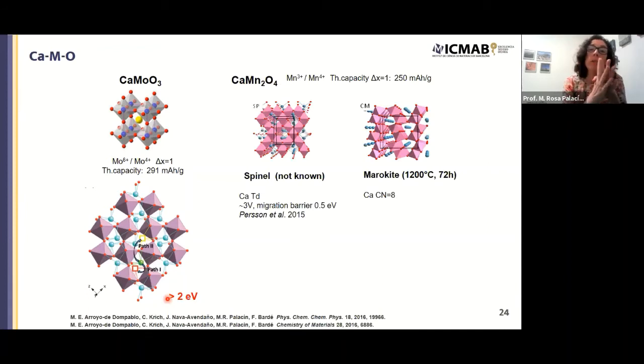Then we became interested in CaMn2O4. This compound had been studied by the group of Kristin Persson. They did some modeling. They assumed that a calcium manganese oxide spinel could form, and if it could form, the migration barriers for calcium would be rather low. This is understandable because calcium would be in a tetrahedral coordination, which is not really expected for calcium. Calcium is too big for that. So that's why it would have a tendency to migrate.